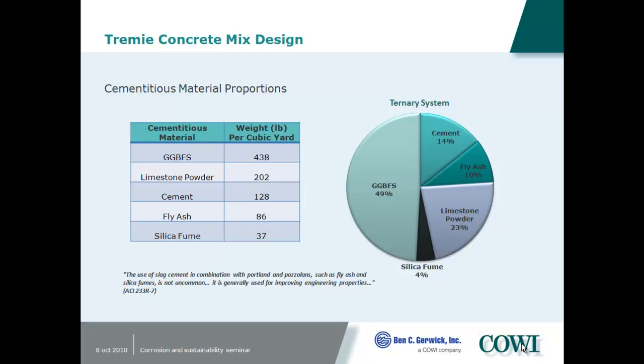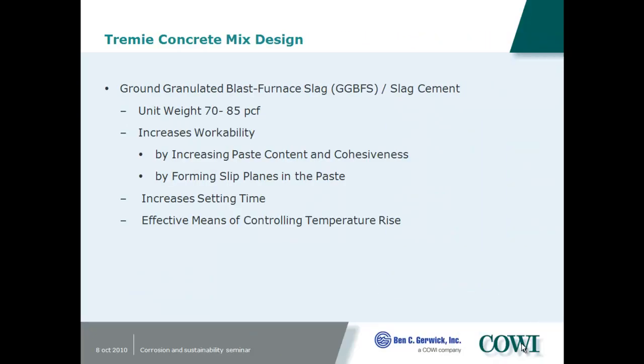This does show that of the cementitious material, half of it was granulated blast furnace slag, only 14% was cement, 10% fly ash, 23% limestone powder, and 4% silica fume. So we only had 14% of a material that was causing a carbon footprint. All the rest of this is essentially a byproduct. But although it is a green mix, the main purpose of this was to control heat of hydration for a massive pour.